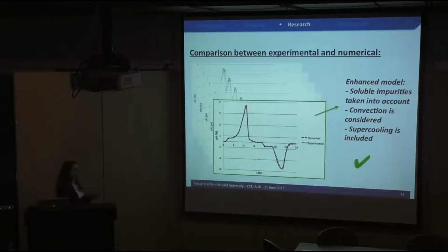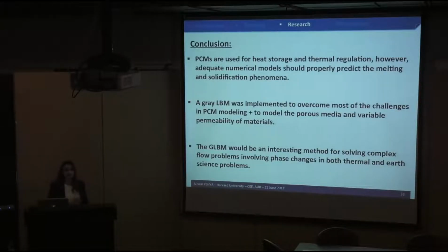So with the enhanced model, we can see that if we use the soluble impurities, the right enthalpy-temperature curve, and the convection is considered, and supercooling is also considered, we can obtain the thermophysical properties. For example, here our degree of supercooling was about 1.2 degrees Celsius. So 1 degree of supercooling was obtained for the 4-hour ramp. So in summary for this part, phase change materials are used for storage and thermal regulation. However, adequate numerical models should be properly developed to predict the solidification and melting phenomena, because convection, if not ignored, can have an effect on the fusion times and also on supercooling.